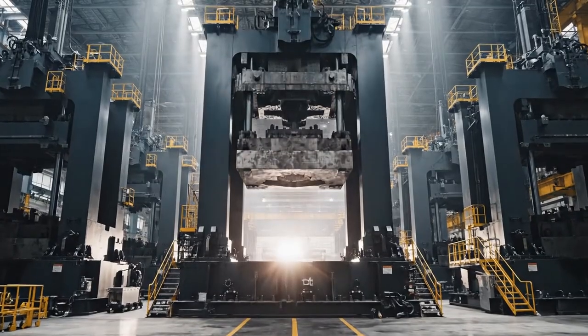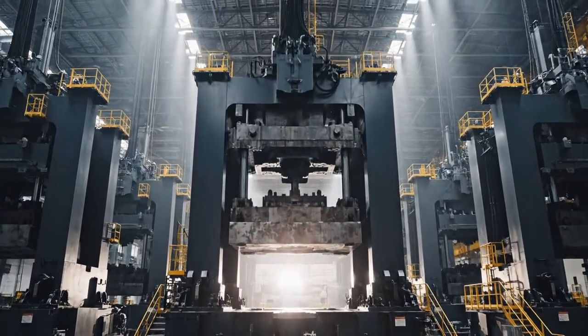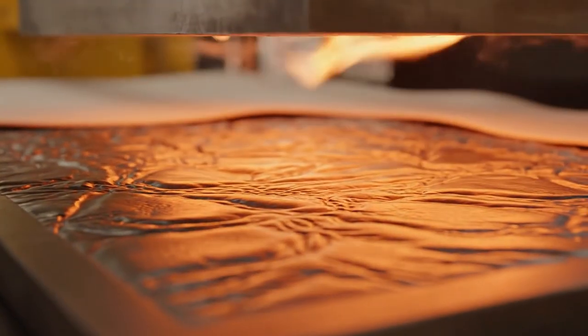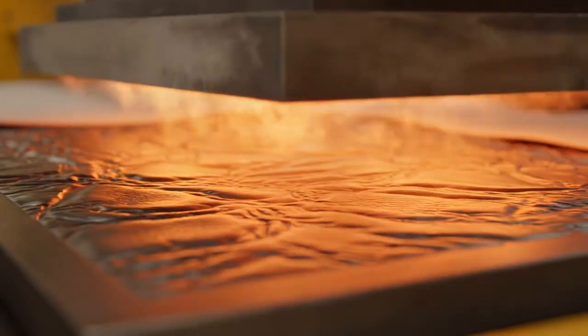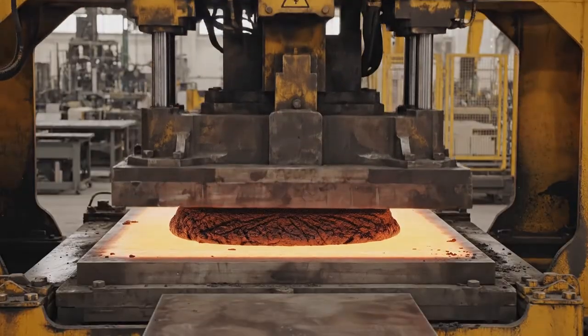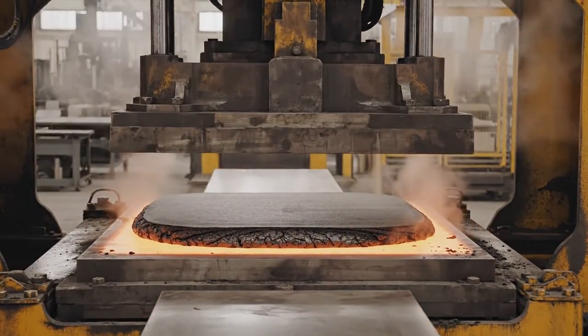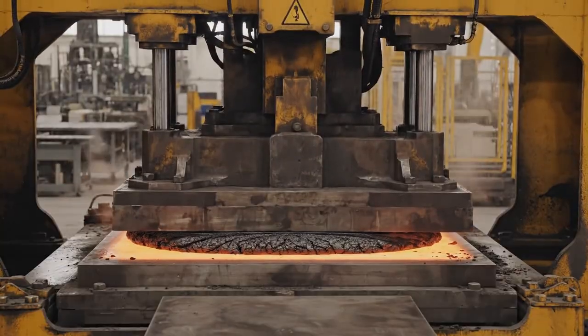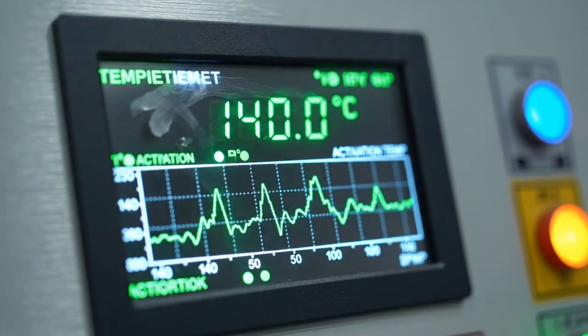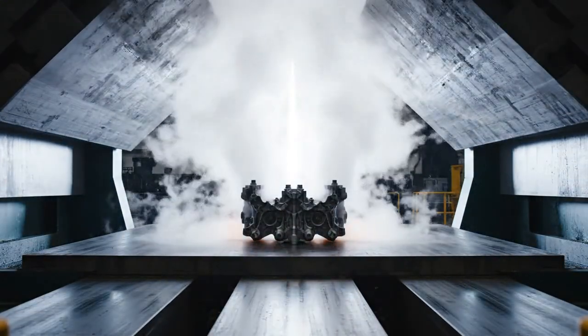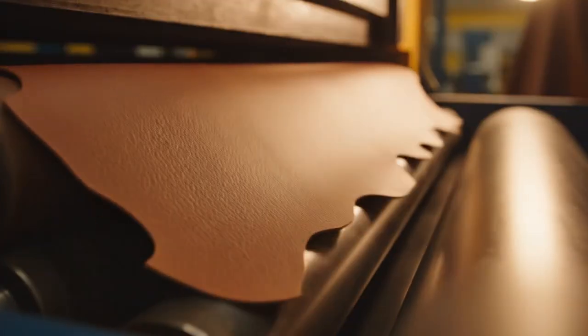Pressure is the next variable. Hydraulic presses, each capable of exerting 1,200 tons of force, compress the paste between heated platens lined with embossed patterns, replicating the grain structure of full-grain leather. The temperature hovers at 140 degrees Celsius, hot enough to activate the polyurethane cross-linking, but cool enough to prevent collagen denaturation. The pressing cycle lasts 17 minutes. When the platens separate, what emerges is a sheet of material exactly 1.2 millimeters thick, flexible, strong, and visually identical to the virgin leather that entered the facility as waste hours earlier.